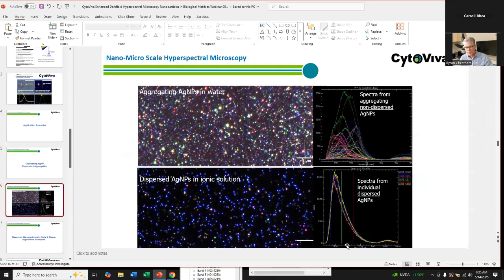If you just look at them in the eyepiece here, here's their spectrum when they're nicely dispersed. And you see how much homogeneity we have in the spectrum across these nanoparticles when they're nicely dispersed in the ionic dispersing solution. When we look at them in water, however, we see that the nanoparticles are aggregating. As plasmonic nanoparticles aggregate or get bigger, they redshift. And so you can see the very smallest particles here appear blue, but you also see green, yellow, red as you see aggregation of these nanoparticles, and likely some oxidation of these nanoparticles is occurring as well in the water media as opposed to the ionic solution.